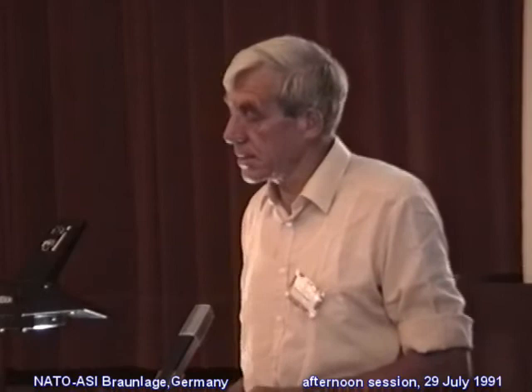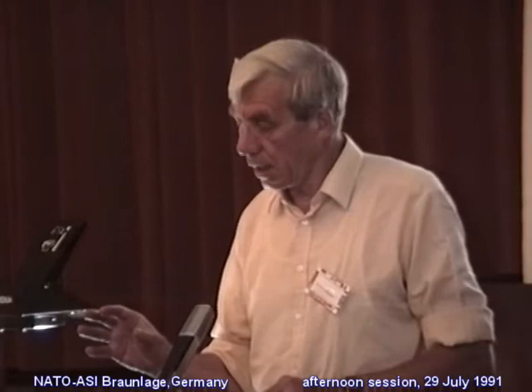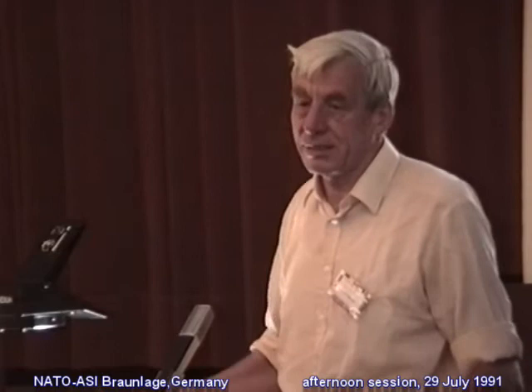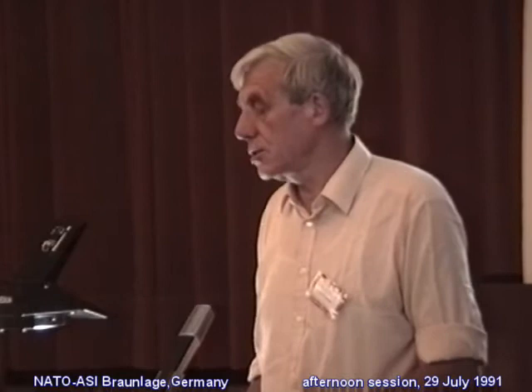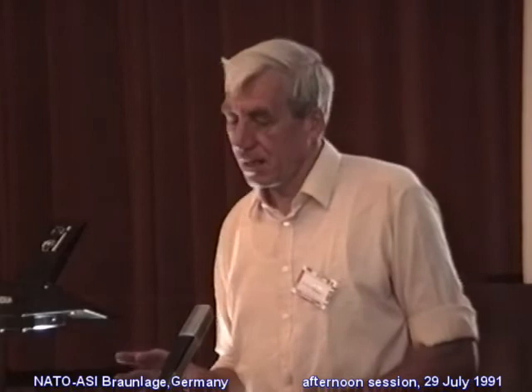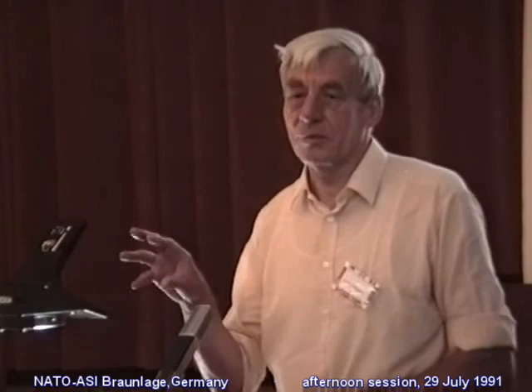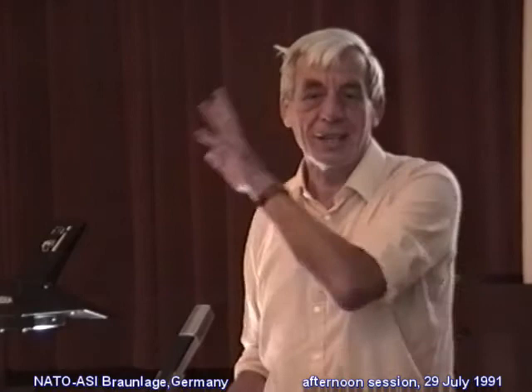Well, I don't think there's an easy answer to that question. The Hertz theory works, provided, and because of the fact that in the circumstances that we've been discussing, the stress zone is very local, and by the time you come to the boundaries of the body itself, or the radius of the sphere, then the stress there is very small. I think it's rather similar to modern fracture mechanics, where one can look at the stress at the crack tip without asking what the shape of the solid is. You can separate out the local field from the distant field.